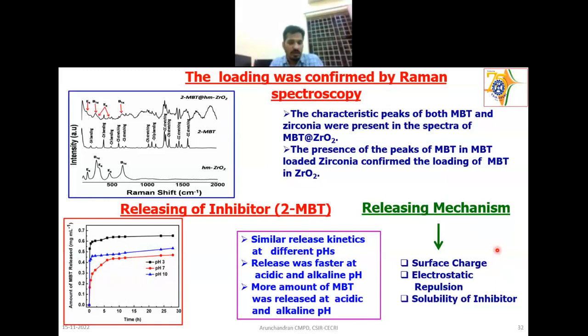If the inhibitor is highly soluble, it will come out quite fast. That should not happen like that. But if the inhibitor is not at all soluble, then you cannot use the inhibitor at all, because when the electrolyte is coming inside, the inhibitor should be able to come out along with the electrolyte.